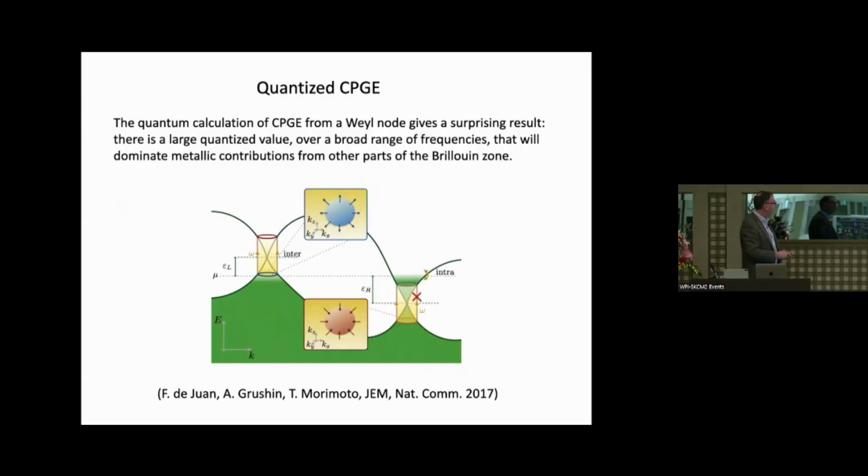In something like rhodium silicide, that will be the hero material for the experiment, it's chiral, and as a result, you can split, say, the positive Weyl point from the negative Weyl point in energy, and then put the Fermi level somewhere in between. So the green is filling up states to the Fermi level. Then what happens, if you think about optical transitions at some finite frequency omega, this optical transition across the Weyl point is allowed. So I should compute it.